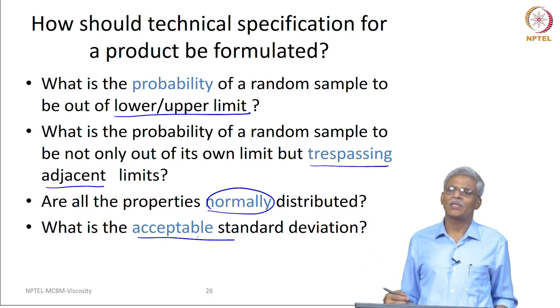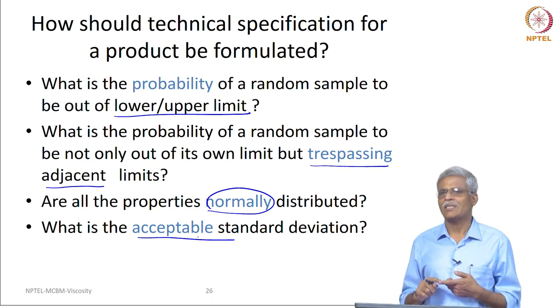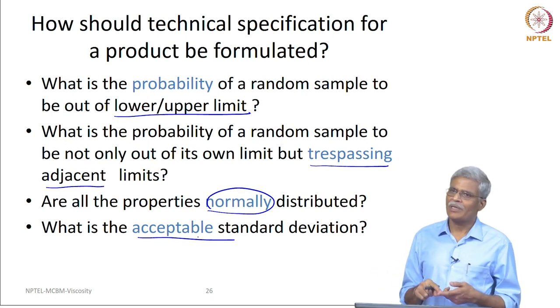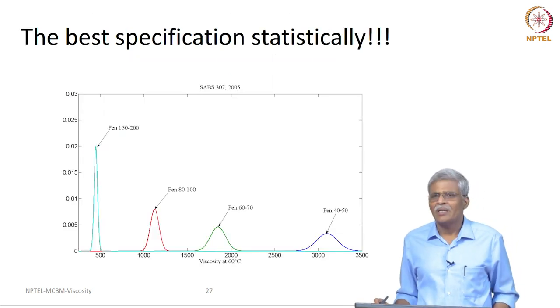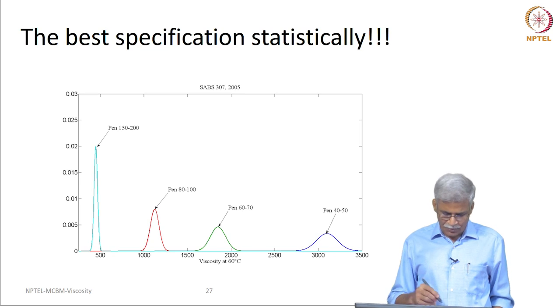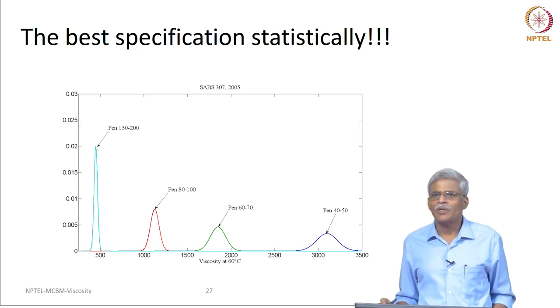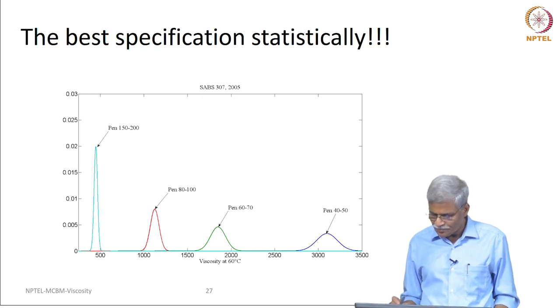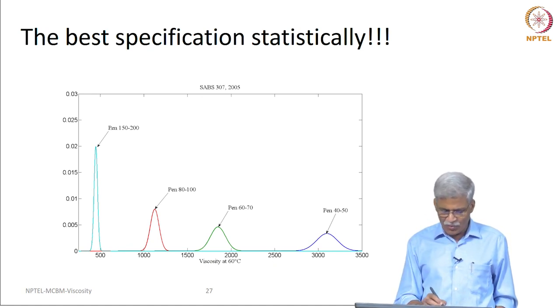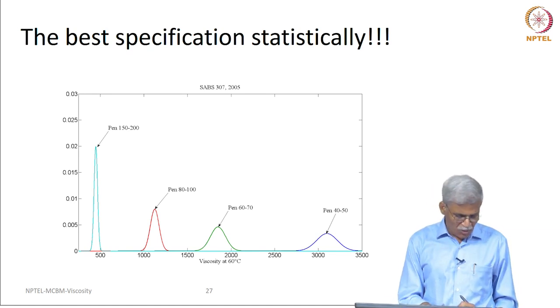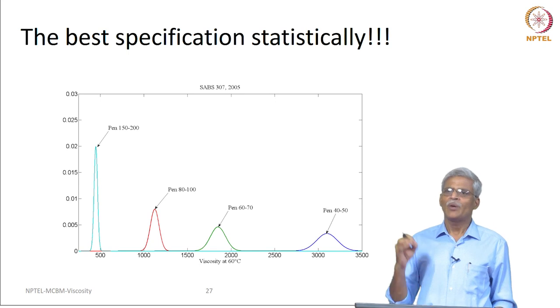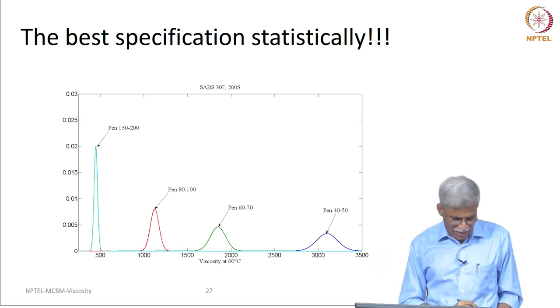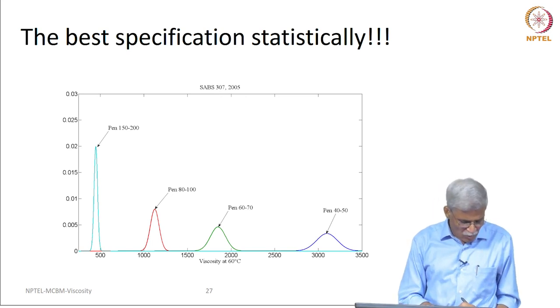This particular slide is presented to make you understand the intricacies related to the production process and the specifications for bitumen. To give a simple example, what you see here is the statistical variations as far as the South African specification is concerned. On the x-axis is the viscosity at 60 degree centigrade, and the values are cleanly spaced out for the different penetration values — there is absolutely no trespassing. Such clear divisions come only when you provide bounds for each and every parameter, but such products are extremely difficult to produce and manufacture.